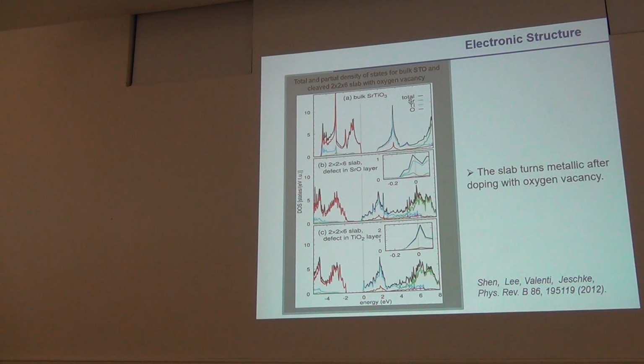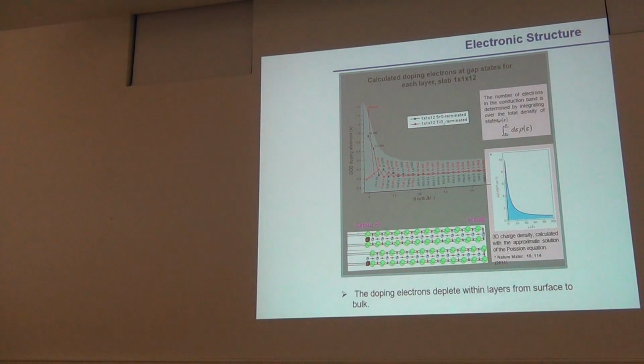But now we need to be a little bit more precise. Let's investigate now how this charge is distributed. And here what I'm showing is one of the slabs that had more unit cells in the z direction, since to reproduce the experiment, they have the surface, but then they have the bulk. Now, to reproduce the bulk, it means I have to put a lot of unit cells to have the information of having a bulk. So here there are 12 layers, so this should be long enough to have at least a hint that we are in the bulk.